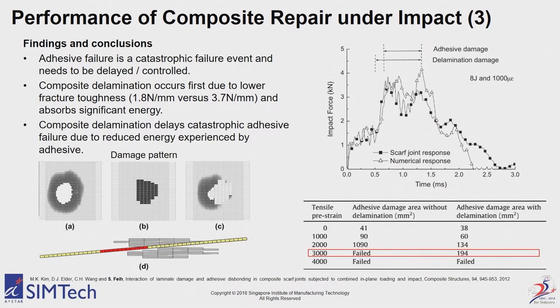And if we actually do a couple of little studies, we can show numerically that the composite damage delays and protects the adhesive joint in the structure. So from that, we can think further and say, OK, we could do more things, like purposely design the composite in such a way that in the critical areas, for example, it absorbs energy before the repair fails. So that was a very important outcome that without simulation you can't achieve, because you can't separate the two things in the experiment. But by validating it against numerical results, we could see which failure mechanism was dominant.